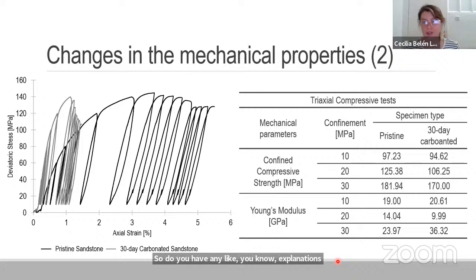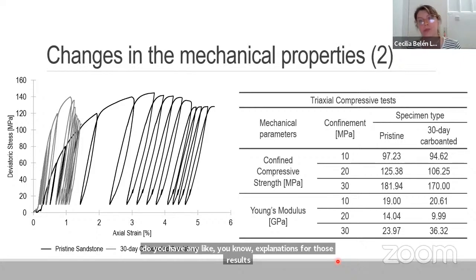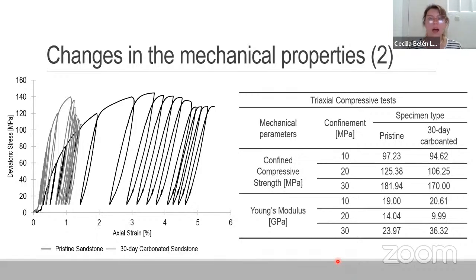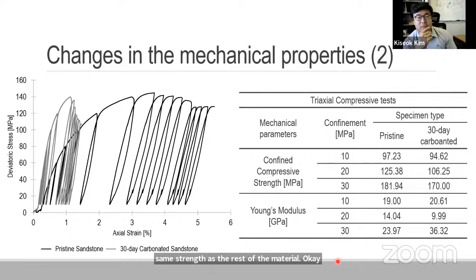Yes, we are still trying to understand it. At first, if you say there is less porosity, you would think that the strength would increase. But the porosity is decreasing because fines are migrating and decreasing the diameter of the bigger pores, and these fines are not as resistant and don't have the same strength as the rest of the material.